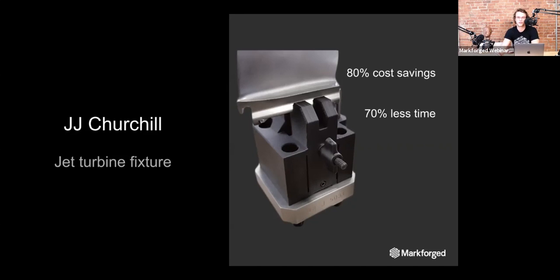And before, J.J. Churchill found that when clamping it into the aluminum, sometimes they deformed the part or scratched the part and had to completely toss it. So they found that when they 3D printed it, they never marred the part, and they actually got higher yield on their manufacturing during the inspection process.